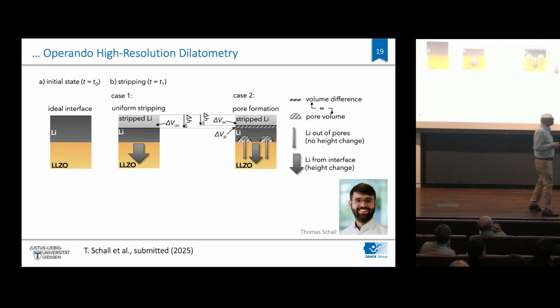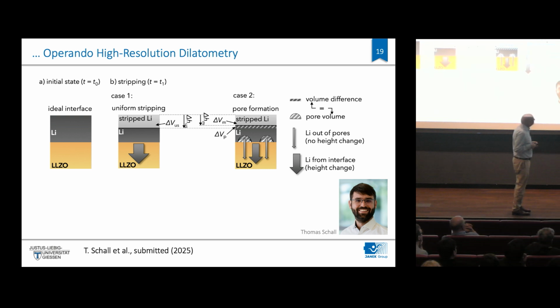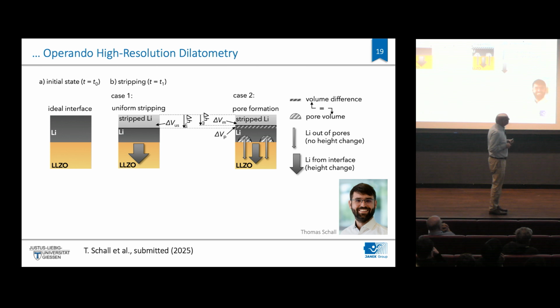Okay, now just one final bit. There's one more little thing, and that is the pore growth. Nobody knows how the pores nucleate. And just a few weeks ago, we submitted a paper. We thought, okay, one of the potential ways to determine pore growth is simply to measure the length change of an anode, very sensitively.